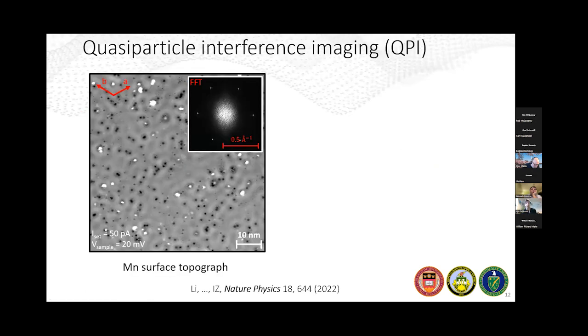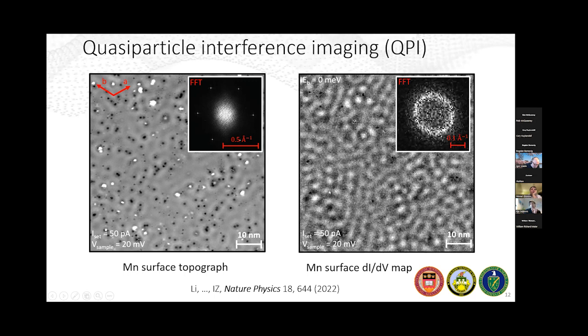So in addition to this momentum integrated technique, we wanted to gain insight into the momentum information of the electronic band structure. For that, we use QPI measurements. It is imperative for this to have a large topograph that you can measure, and this is exactly what we have here. And then we measure a dI/dV map. This is the one acquired at the Fermi level exactly. And then we perform the Fourier transform. The Fourier transform of this image on the right leads us to just a single circle centered at the center of the Fourier transform.